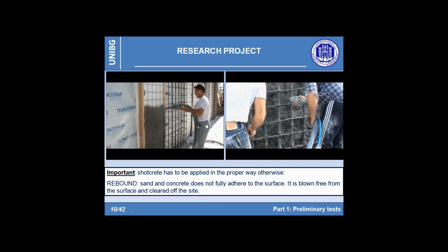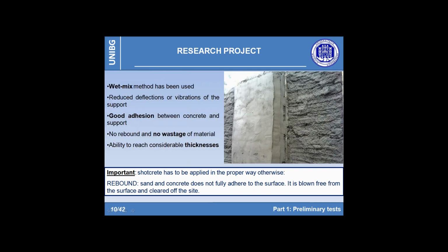First of all, the worker has to pay attention to correctly regulate the amount of the compressed air flow. Otherwise, the impact forces become too high, and this can result in deflection or vibration of the support that can also imply a rebound and thus a wastage of material. This test, in particular, relies on the assessment of the feasibility of the process, monitoring initially the capacity of the cementitious compound to adhere to the supports and to show limited rebound.